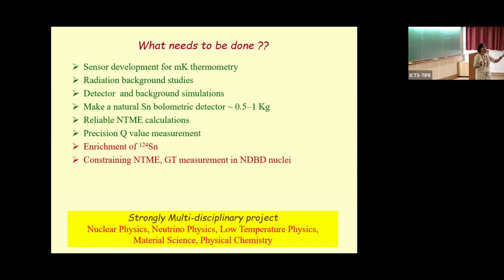But for the other nuclear lower isobars, I won't get that. When you have other elements present, remember you have gammas and neutrons in the surroundings. Whatever we do to minimize it, it is not going to be zero. They will be there, and those neutron-induced reactions will create a background field. So if I don't have enriched tin, there will be reactions on 116 tin which generate indium 115, which will have a background. Whereas if I go for enrichment, I would deal with background or issues coming only from 124 tin, and I will get as much as possible remaining out.